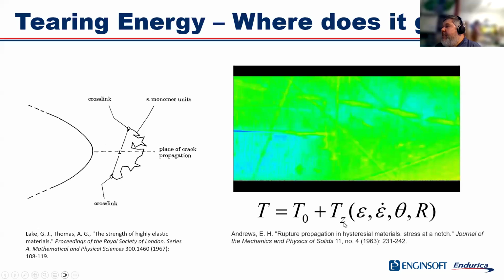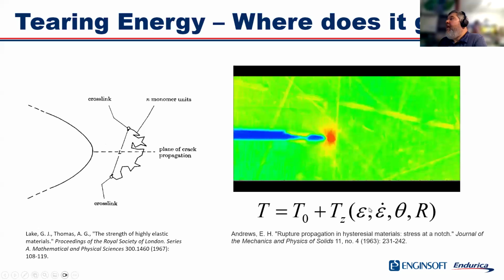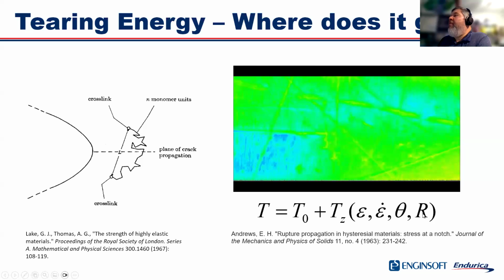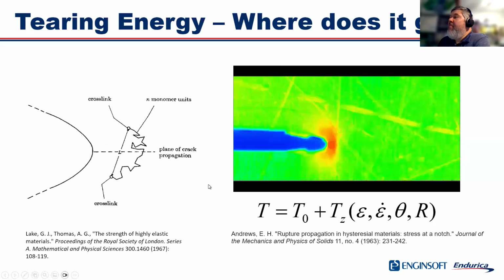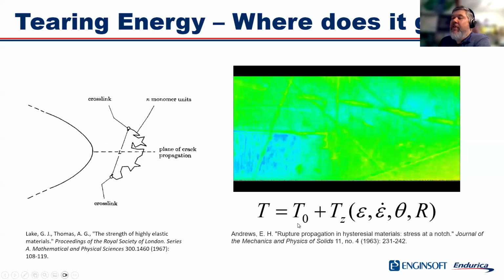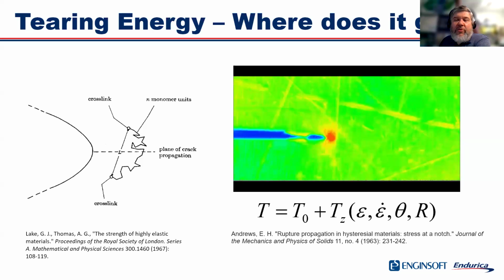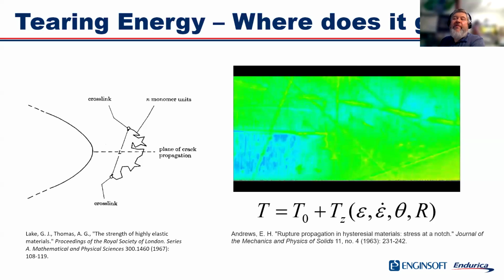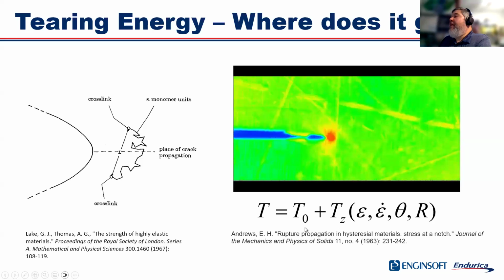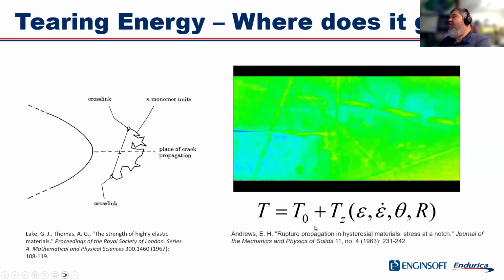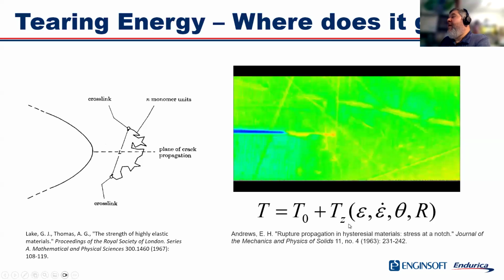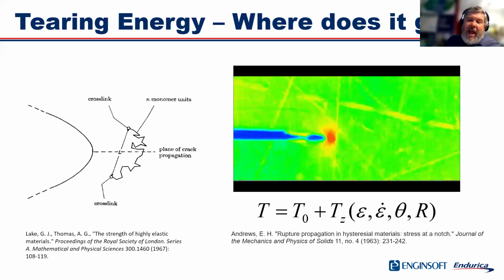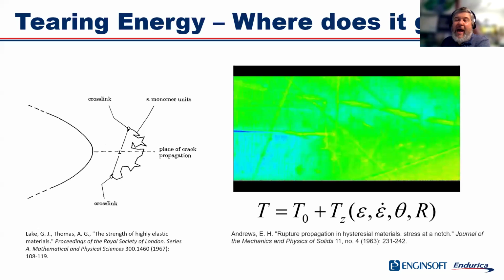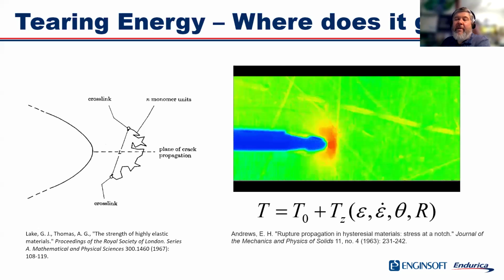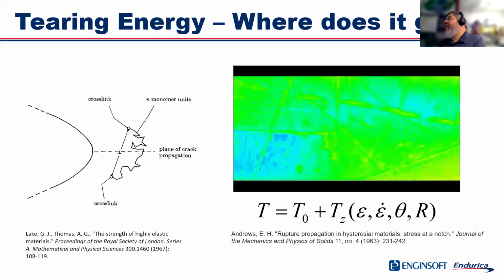And you can see this TZ term. This is the part of the energy that comes from that process zone. That is depending on strain rate, temperature, R ratio, and so on. And I'll say that T naught for a typical rubber might be of the order of maybe 50 joule per meter squared. It's actually quite a small number. 50 joule per meter squared is not that much. Depending on how fast the crack is growing, TZ can be bigger or smaller. If you're propagating the crack at a very high rate, TZ might be as high as like 100,000 joule per meter squared. And then of course, as you back off, that can be quite a bit smaller too.